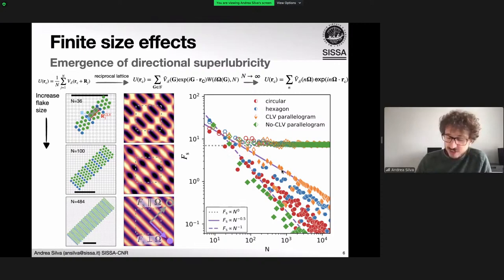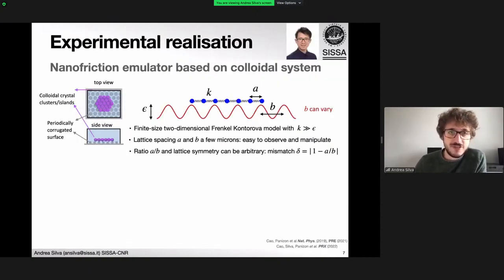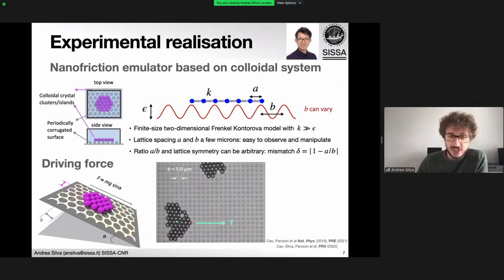So we're still very much in a theoretical world. I just wanted to give a couple of examples where we saw this in a more real system. Not quite a nanoscale interface, but what we call a nanofriction emulator, which is a colloidal system that emulates a real atomic interface, where we have these colloidal clusters over a patterned surface, where we can tune the symmetry and strength of the substrate potential, mimicking two crystals basically meeting and pressed against each other. We can drive it like in a friction experiment using gravity, and we can see that this cluster moves along the patterned surface along a specific direction, here going with some directional locking.